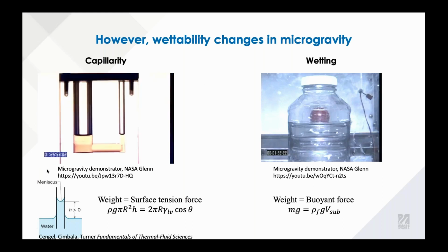So here I have two videos. Hopefully they'll work. So they're both drop tower experiments, and here, if you play the video, maybe it'll work. Okay. So what's going to happen, I hope, is that you'll see a capillary tube, and what happens when it goes through a drop tower and it experiences a lower gravitational force. And so if you saw in the capillary tube, there was this large rise in that height. Typically, when we do a capillary tube experiment, we put a capillary, so it's a small diameter tube, into a liquid, and if it's a wetting fluid, then the height rises. If it's non-wetting, then the height drops. And what's happening here is we're having this force balance between the weight of the fluid and then the surface tension forces.